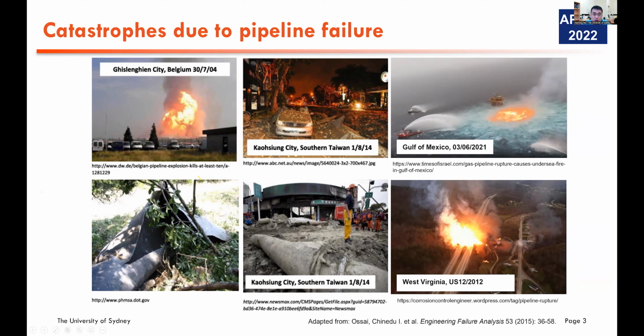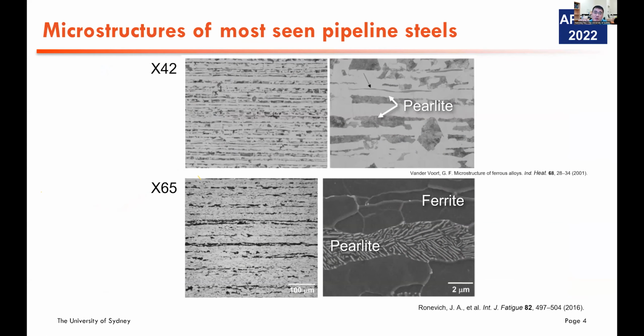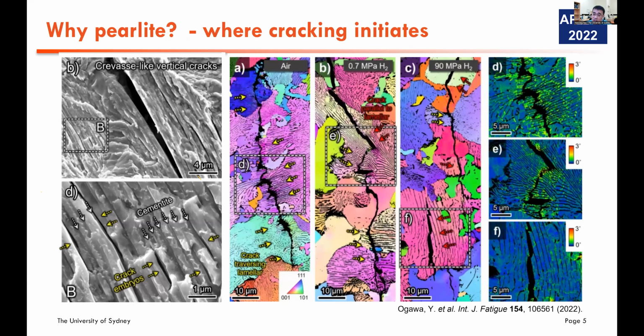So what can we do about it? From a materials science perspective, we look for the reason in the microstructures of materials. In the literature, the most commonly seen microstructures in pipeline steels are ferrite, which is a phase, and pearlite, a microstructure constructed of lamellar ferrite and cementite phases. These are interesting because the literature shows this microstructure is exactly where cracks initiate after hydrogen charging. As you can see in the SEM images on the left showing the fractography of a hydrogen-embrittled steel after tensile tests and failure, those cracks or crack embryos were found in the pearlite microstructure, mostly at the ferrite-cementite interface.